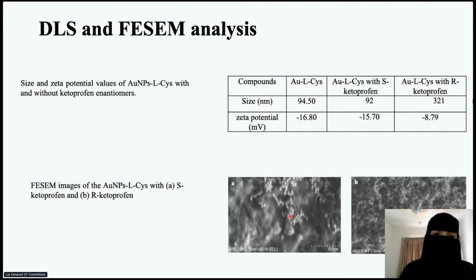Also, FESEM shows the same thing with S-Ketoprofen. There is not much aggregation. However, with R-Ketoprofen, a huge aggregation happened. That's aligned with the UV-Vis, the appearance of the new peak, the new peak of the FTIR, and the new peak of the Raman spectra. All show the aggregation and the selective response toward only R-Ketoprofen.